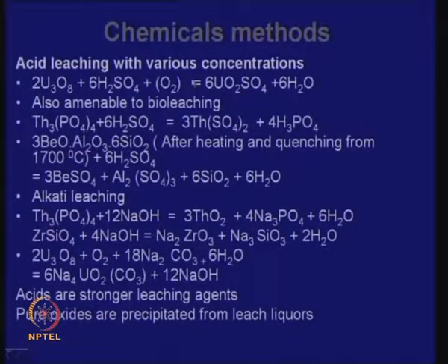Remember I had mentioned, there are all kinds of bacteria which can speed up the natural process of sulfuric acid leaching of oxide deposits. This work is also going on in our country, where there are low grade uranium ores. We can identify some bacteria, and those bacteria, if left there, will leach automatically. It will be very much suitable for low grade ores, because it will produce a leach liquor. We would not have to go through elaborate processing, but that is a long run process.